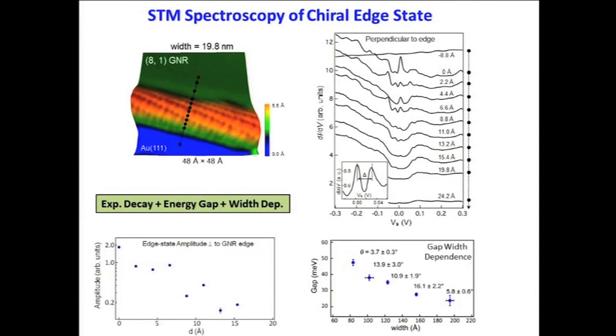However, even if it's terminated with different atoms, at some level you still expect these edge states to exist. Because if the termination is just bonded to that sigma bond sticking out, as long as the pi network is not all messed up, then we still expect this edge state to occur. So that will lead to bond bending on the graphene. And in that case, you notice that there is a bump at the edges. This curvature, that's structural. That will be a natural consequence of the electronegativity. It will decay in an oscillatory manner inside the ribbon. A lot of the observations will be the same with a classical model.